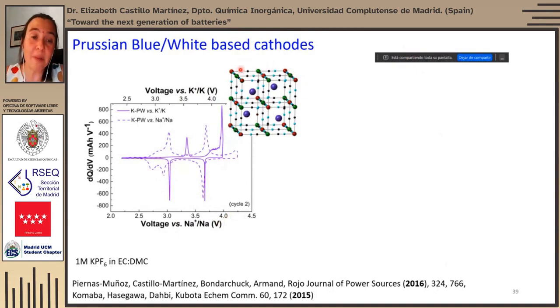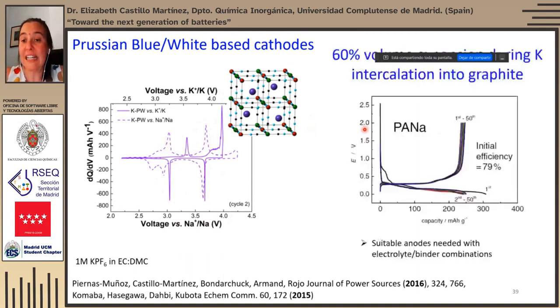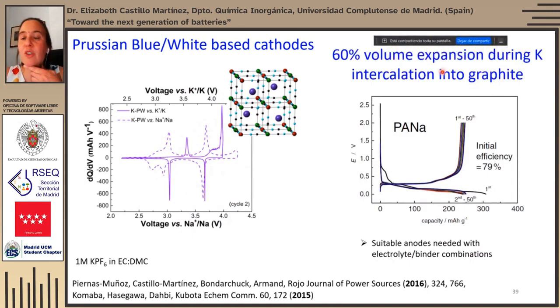For potassium-ion batteries, the Prussian blue materials are the preferred cathodes because their tunnel size perfectly matches the size of the solvated potassium ions. And you can see that the voltage is quite higher than that. The voltage of insertion of potassium ions is higher than the voltage of insertion of sodium ions in the same site. For the anodes, graphite does show a 60% volumetric expansion when potassium is intercalated into graphite. It's quite large, and therefore it is also interesting, and this is one of my current research areas, to look for alternative anode materials for potassium ion batteries.